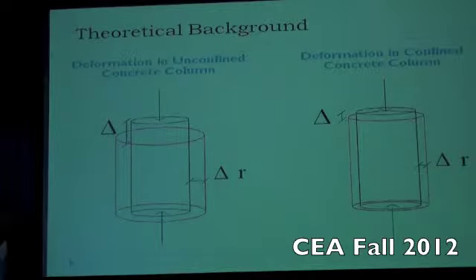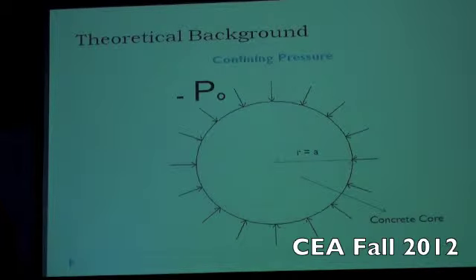I'll explain the theoretical background for our experiment. Normally, in an unconfined concrete column, axial shortening takes place, and due to Poisson's effect, transverse expansion takes place because the volume of the specimen must remain constant. When the specimen is confined, the transverse expansion is less, and therefore, to maintain the constant volume, the axial shortening is less too. And this makes the concrete core stronger.